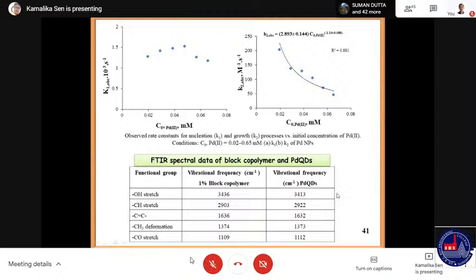There are no new kind of peaks appearing. This means that palladium quantum dots, palladium does not form any kind of bond with the block copolymer functional groups or moieties. It is only being stabilized or encapsulated in the micellar system of the block copolymer.